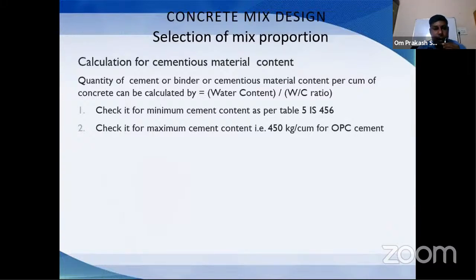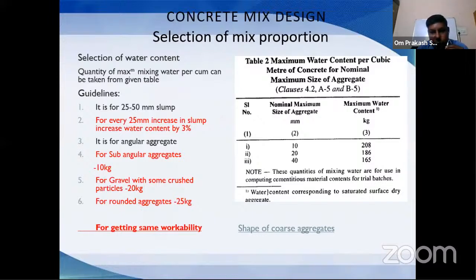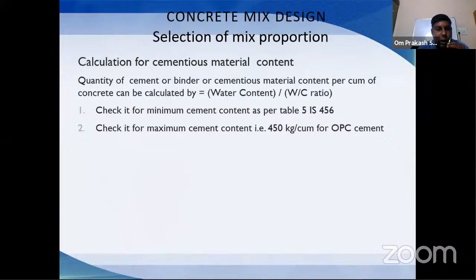Now, we have found the water content. Next is the quantity of cement. Let's say we found the water for 20 mm is 186 kg, and we are taking the water cement ratio as 0.5. What we have to do is divide 186 by the water cement ratio of 0.5. It will come to around 372 kg. That will be our cement content.